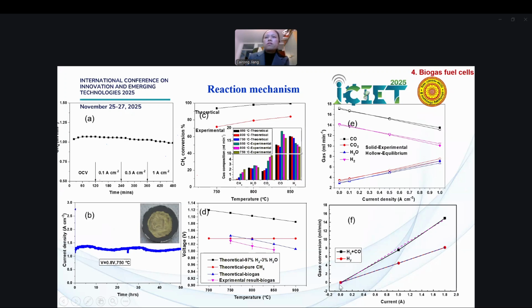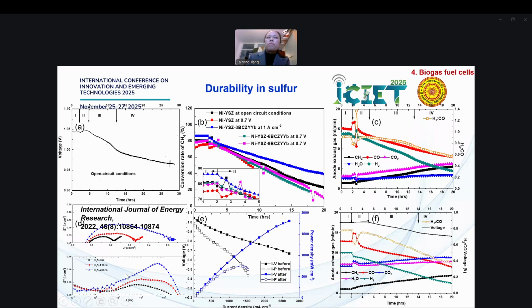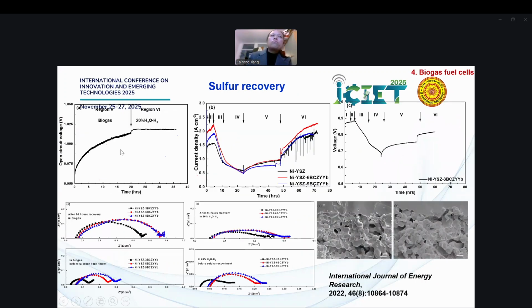And we also did some research on the reaction mechanism, and this can either consume hydrogen or, at high temperature and high current densities, consume both hydrogen and carbon monoxide. So we really get a good cell, and carbon monoxide is one of the fuels. This we learned from this cell. And the durability is good in sulfur. For 20 hours, and even more than that, there's some degradation. You can see the line drop a bit every hour, and here it recovered so quickly when we removed the sulfur, and it even recovered to better than the original value, as seen in picture B. And we tested with SEM, and there's no carbon coking in the SEM picture.